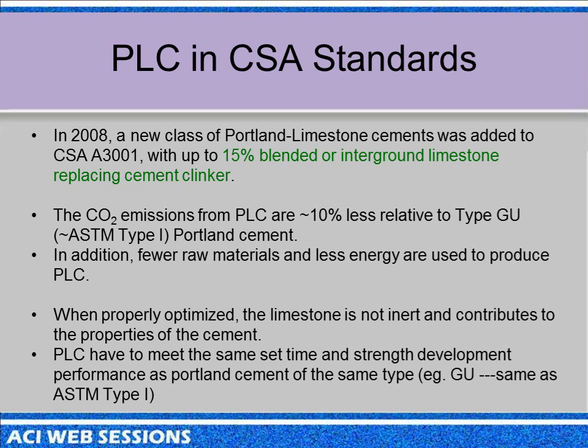So, in Canada, the Canadian Standards Association, which is equivalent to ASTM, in 2008 came up with a new class of cements, Portland-Limestone Cements, distinct from Portland cements. We still have Portland cements, but we developed a new class of Portland-Limestone Cements in our standard, which is A3001, which contains up to 15% blended or interground limestone replacing clinker. Actually, we just got rid of the blended. It has to be interground because that's what the data was based on.